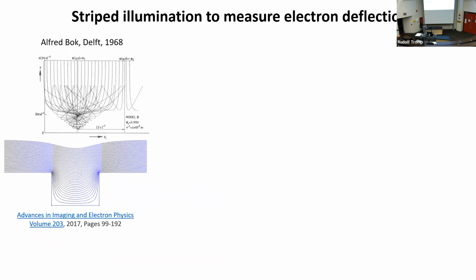When we do this experiment, so here we have a trench in a sample, and these are the equipotential contours that I calculate in front of the sample. Remember, there's always a strong field between the sample and the objective lens, right? 10 kilovolts per centimeter. And here you see these equipotential contours. This is an experiment that Alfred Bok did in Delft in 1968, using an analog computer because there were no digital computers at the time powerful enough to do a ray tracing calculation.